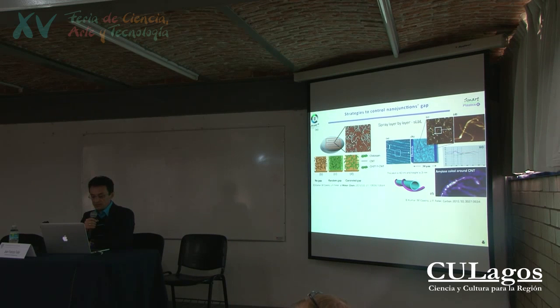To do that, we have developed a particular technique, which is the control of the junctions between the nano objects. The electrons are circulating in the network of nanoparticles, and they are jumping from one particle to the other. So if you control the way the electrons are jumping, you can control the properties of the sensors. So we developed different strategies to coat, to chemically graft carbon nanotubes. And particularly, we achieved the coiling of the nanotubes by natural molecules like amylose. Amylose is a polymer that you can find in starch, in flour. This molecule is known to be able to make coils, to make helices. So you can use these helices to coil the nanotubes.